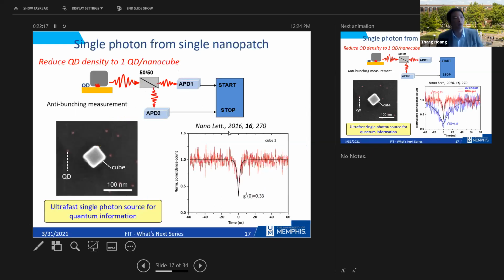And also, if you want to make a single ultra fast photon come from this quantum dot, we can try to reduce the quantum dot density on the sample until we have only one quantum dot beneath the nanocube. Then we have one quantum dot only able to emit one photon at a time, and we use a setup we call the anti-bunching measurement, which does a kind of start and stop. The graph down here shows an actual sample that we see, the nanocube, and the quantum dot is very diluted. So we hope that there's only one quantum dot underneath the cube, and then we do the anti-bunching measurement.